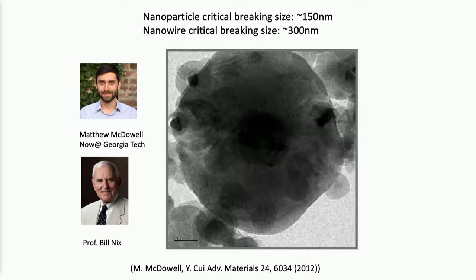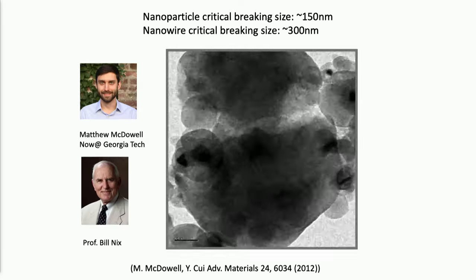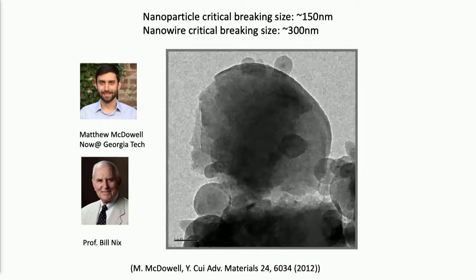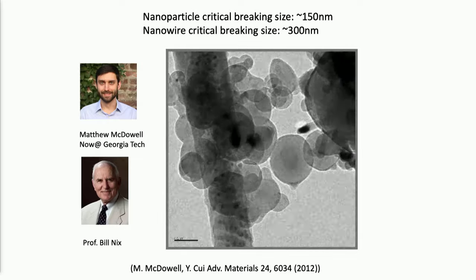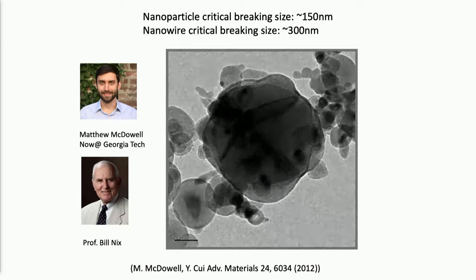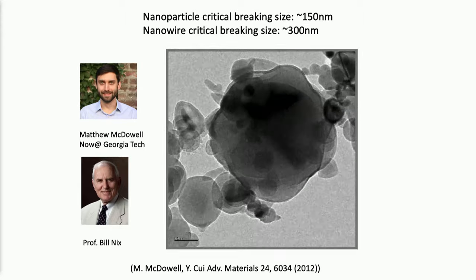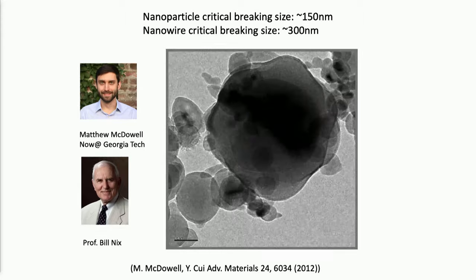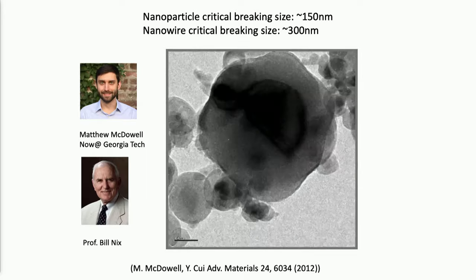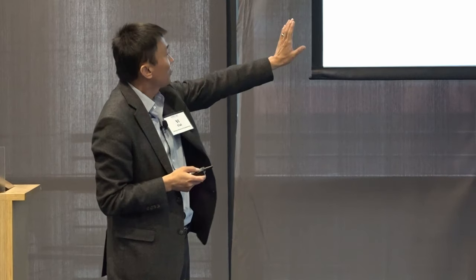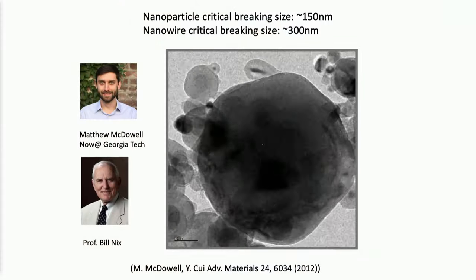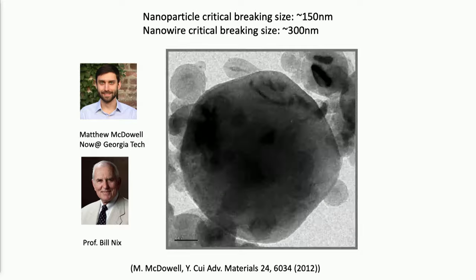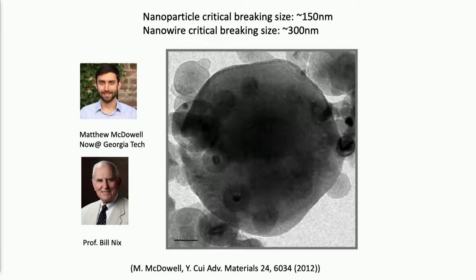Once it's broken, materials lose connection with each other, and then your capacity is gone. So basically, with silicon, the first time you charge your battery, it's already dead, right? Then it doesn't work. So you need to avoid this breaking. So utilizing this tool, we actually identified the size scaling law, how small you need to make this particle in order to avoid breaking. It turned out to be about 150 nanometers.